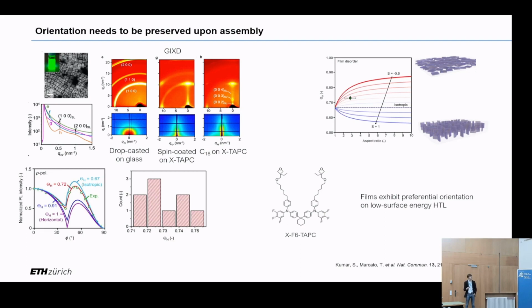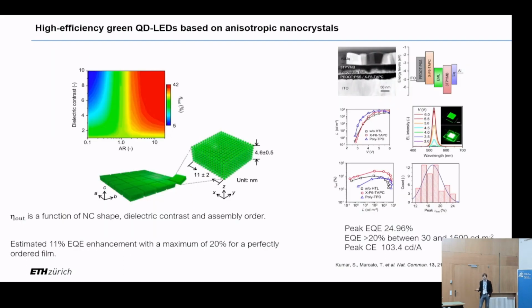So you see, you have the maximum if all the nanocrystals lie horizontal, but if you play with the assembling film, you have, of course, a huge variation. You can achieve a completely isotropic emitter. So at the end, we were able to direct the assembly of this nanocrystal by spin coating on top of a low surface energy hole transport layer. And we observed emission with an anisotropy factor up to 75%, which means 75% of the dipoles are in plane. And the next step was, let's use this system in LEDs.